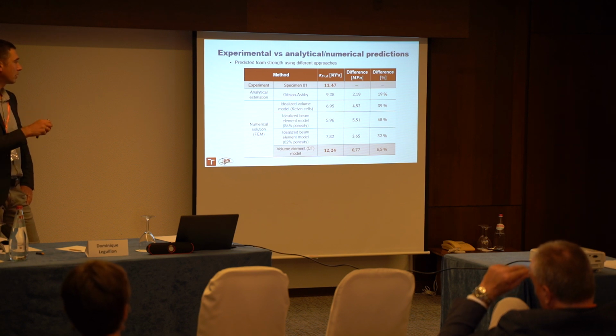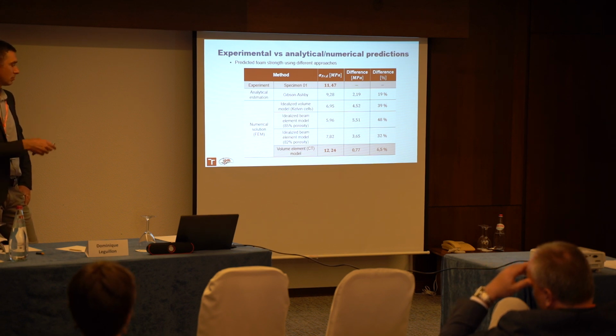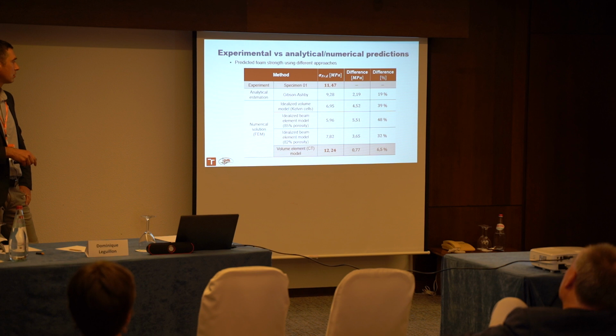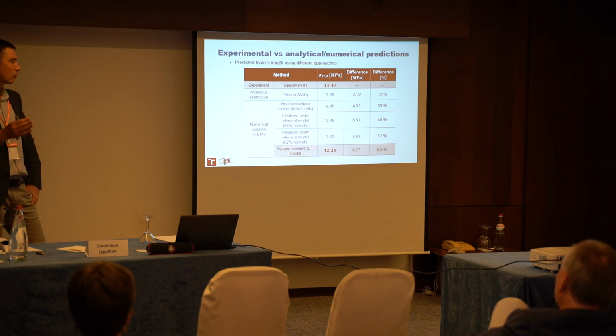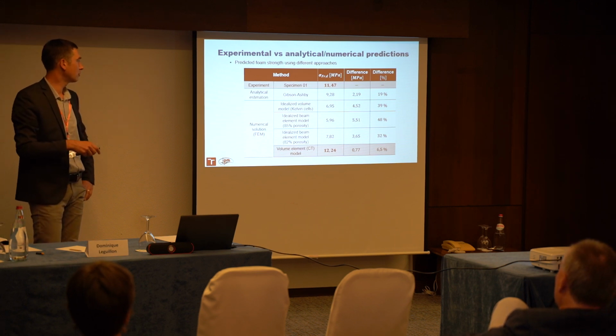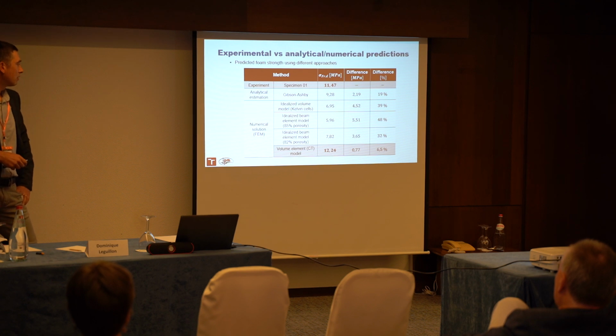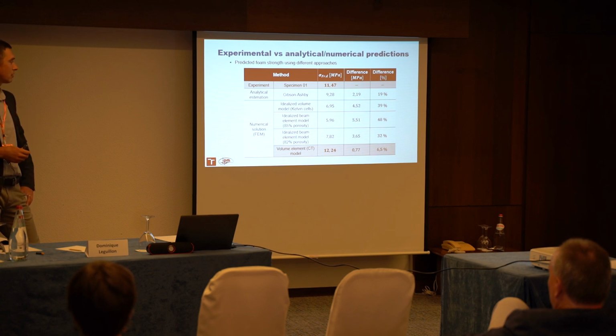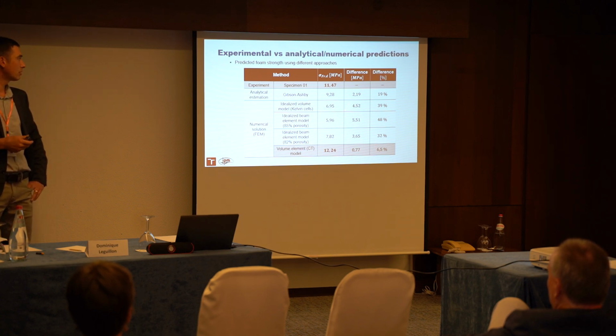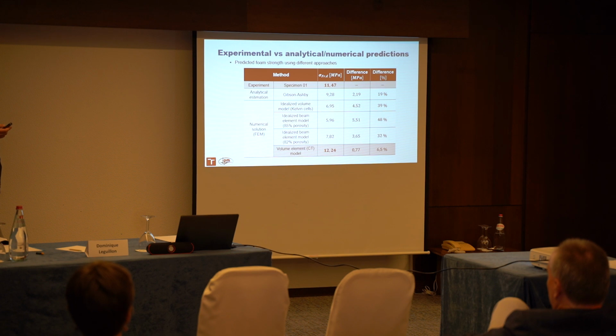Then we tried also to model the foam using some volume model. There was also not very good agreement. When we used the beam element model, the agreement was even worse. And the best agreement was found in case of this finite element model. We had a difference of just around 7%, so it was for us a really satisfying result.